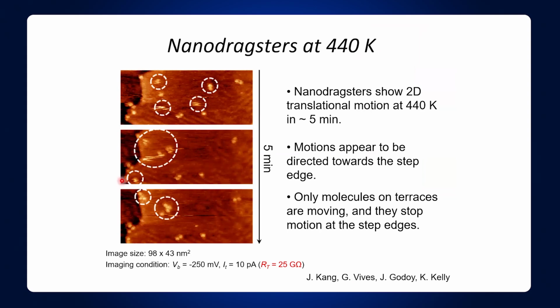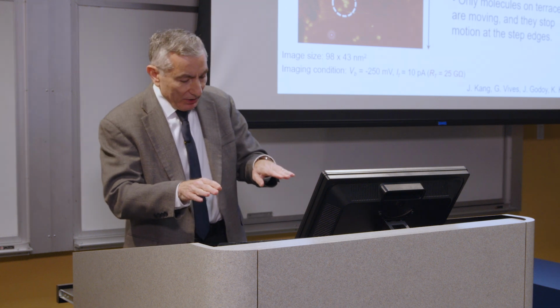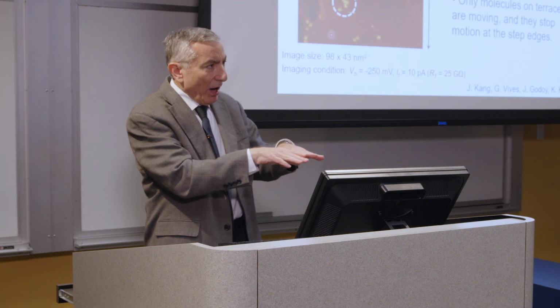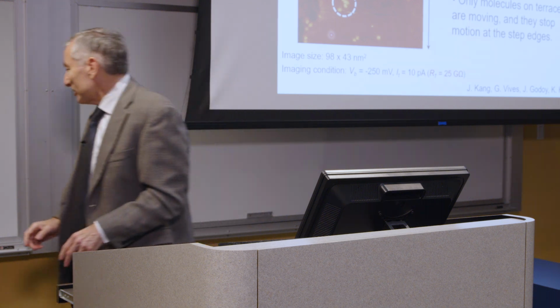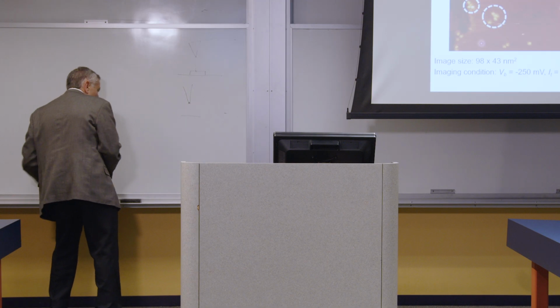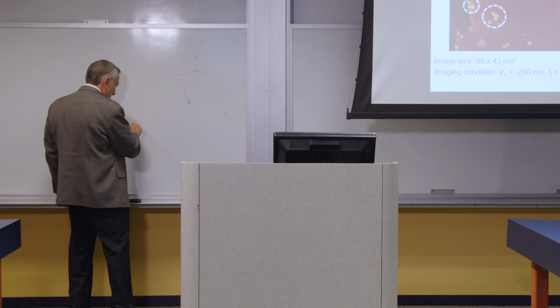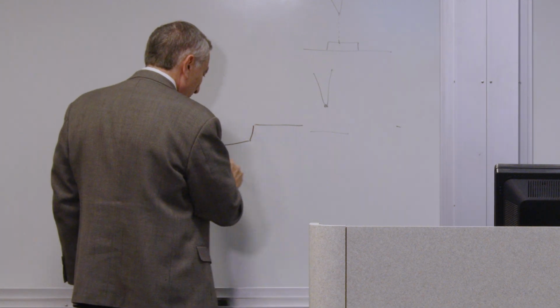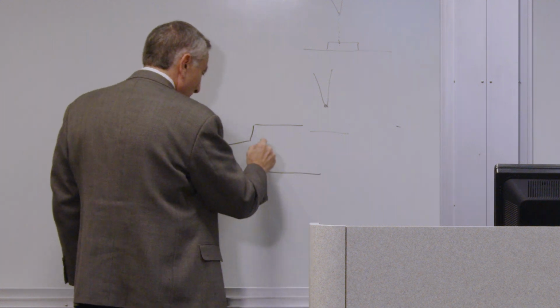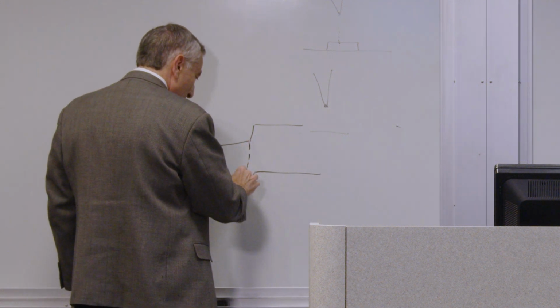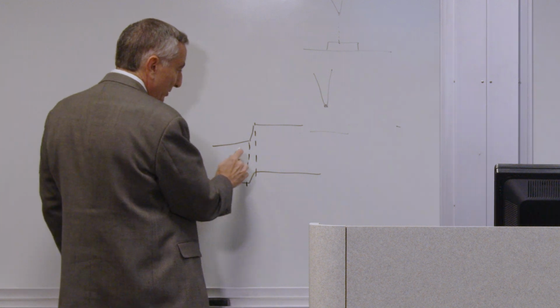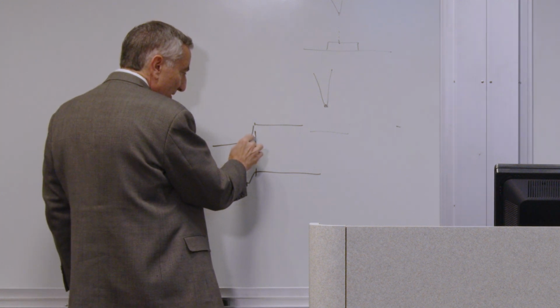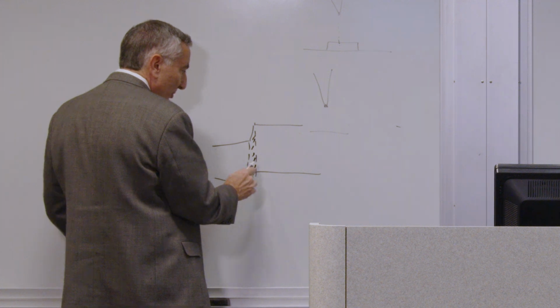So here's the dragsters at 440K. Here's the step edge. And what happens is you heat them up, and they all start moving toward the step edge. And why do they move toward the step edge? It's because you have this terrace that's one atom step high. And right at that terrace, so you have this plane, and then you have another plane. And so you have a terrace here, and you see these atoms across this terrace.